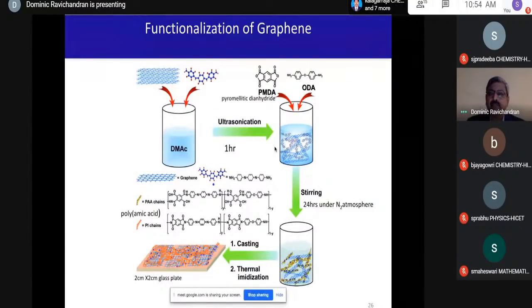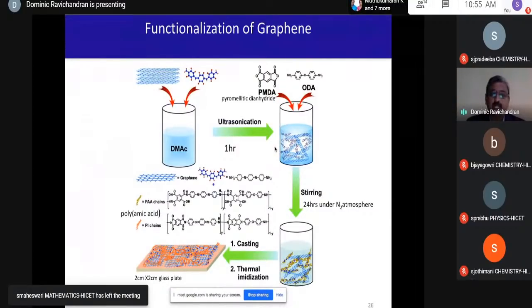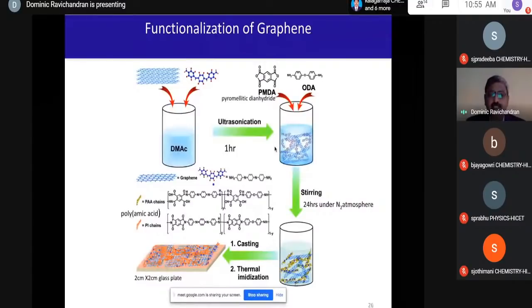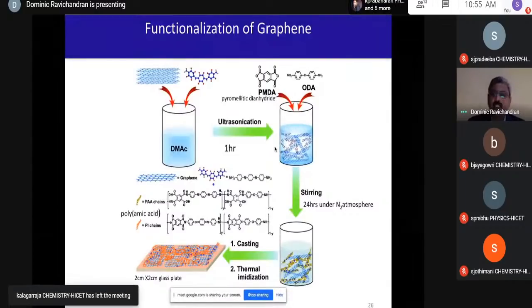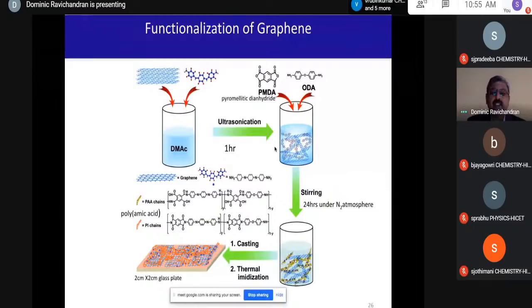Once this is done, we add what is called pyromellitic dianhydride and oxydianiline, which is 4,4-oxydianiline. Mix these into this mixture and keep it stirring for 24 hours in a nitrogen atmosphere to get what is called polyamic acid graphene composite or polyimide chain graphene composite. And once we get this graphene composite, it can be cast onto a glass plate of 2 centimeter by 2 centimeter size and air dried under nitrogen atmosphere so that we get the sheets of composites.